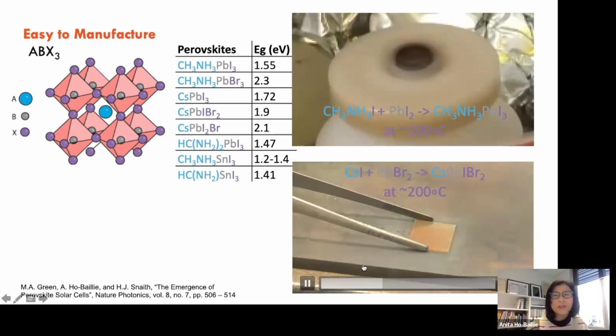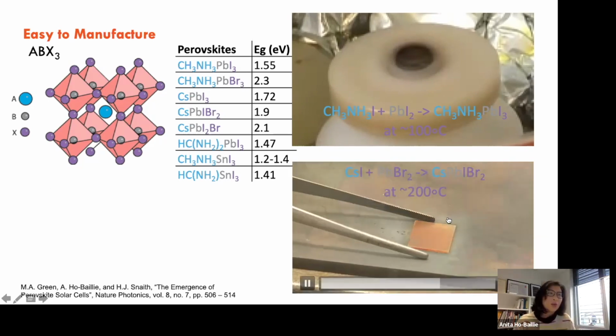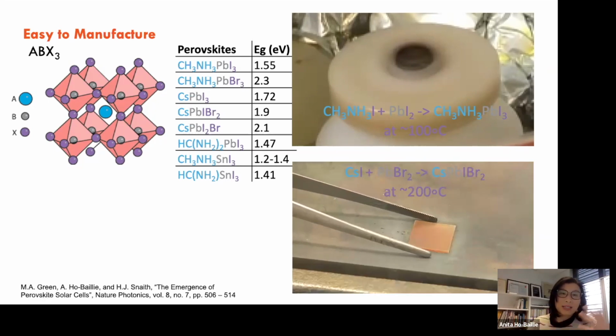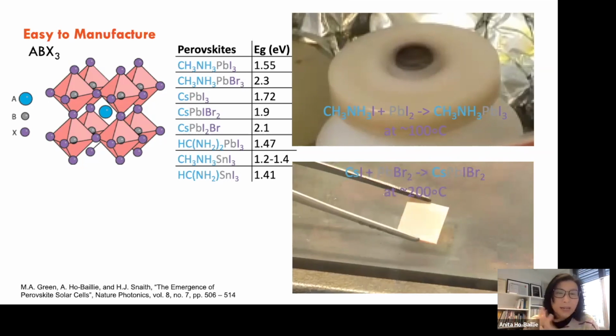You can see on the bottom video that my student is spraying a precursor onto a substrate, and you can see it changes color. What it means is as soon as it sees some temperature, it helps the material to crystallize, to form that chemical crystalline structure, perovskite, which self-assembles at 200 degrees, and it's photoactive. So voila, this is a solar cell, and it's orange in color because it's got a band gap of around 2 eV that absorbs anything that is orange and with energy above the 2 eV.